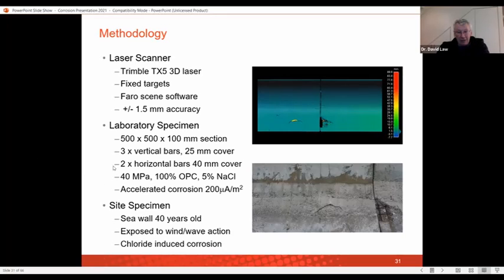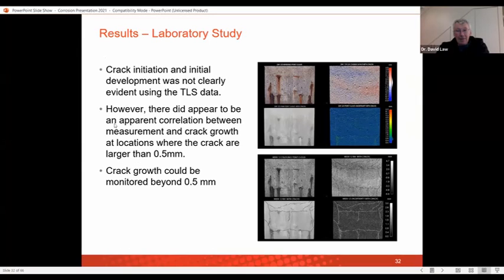And so these are some of the data that we had. So we had a set of bars that were in our laboratory specimen, and we put in 5% sodium chloride, and we accelerated our corrosion with 200 microamps per meter squared. The seawall was 40 years old, and it's got quite bad chloride-induced corrosion in it. And thus, we were able to do a set of scans, and you can see here where we can use the resolution of our laser scanner to actually pick up the crack patterns that we had on the blocks themselves.